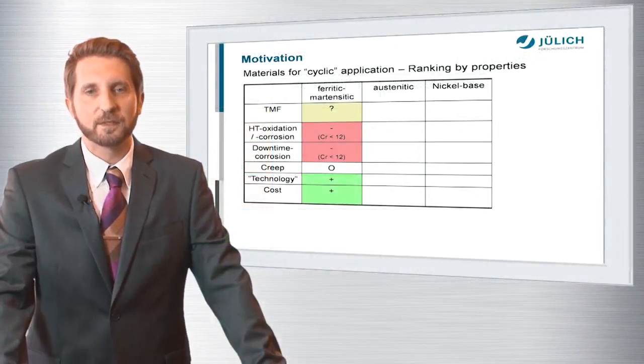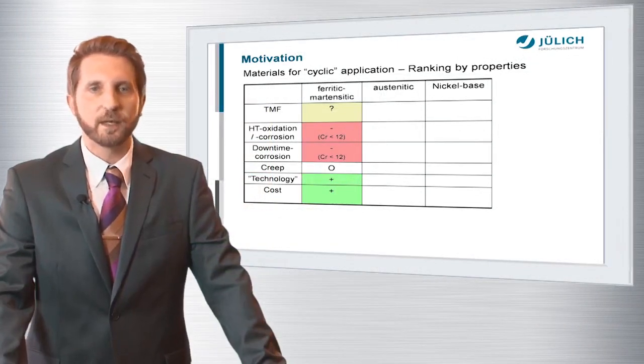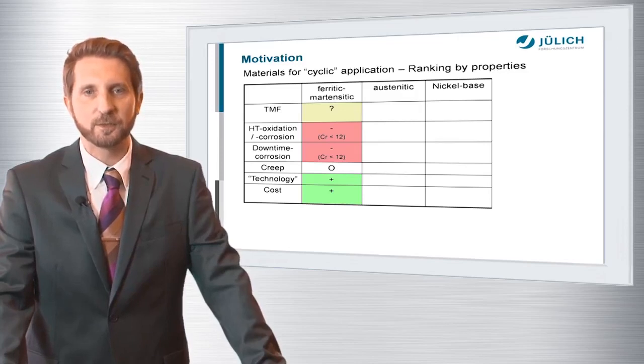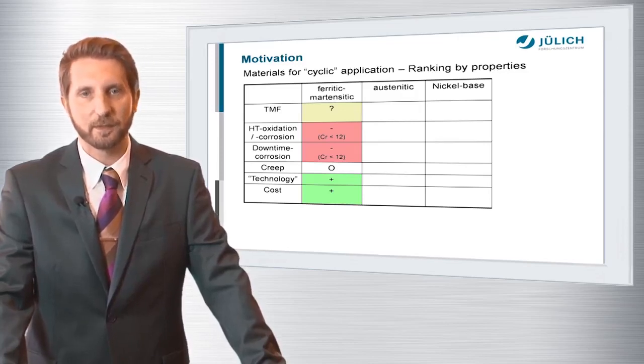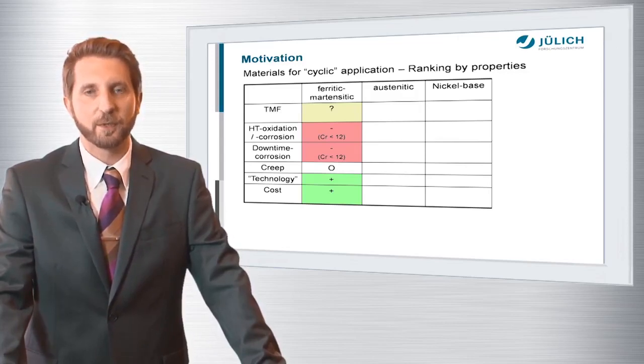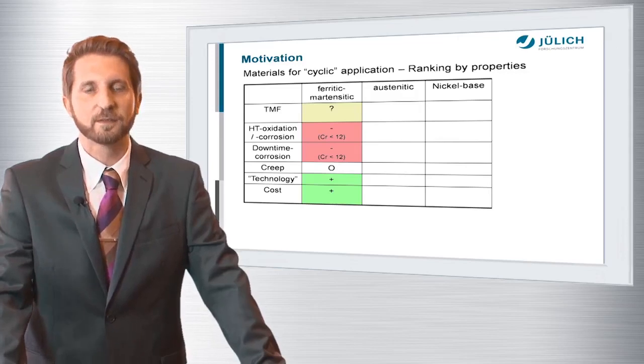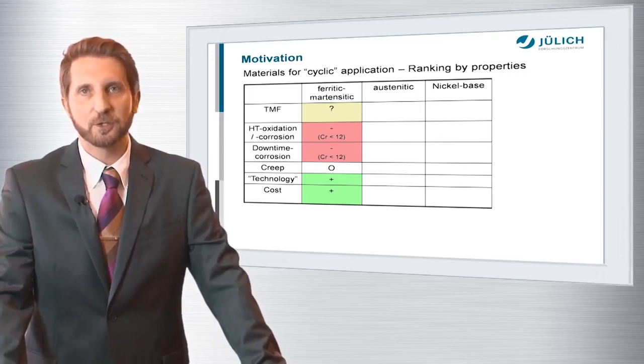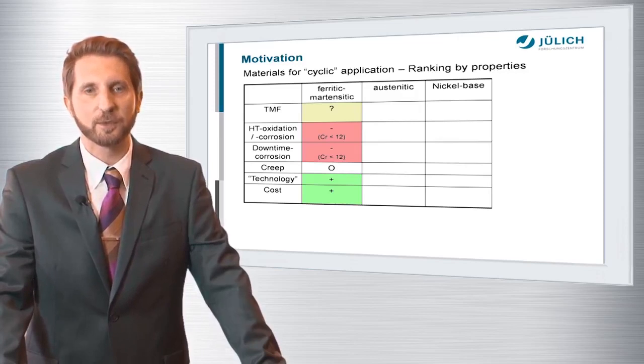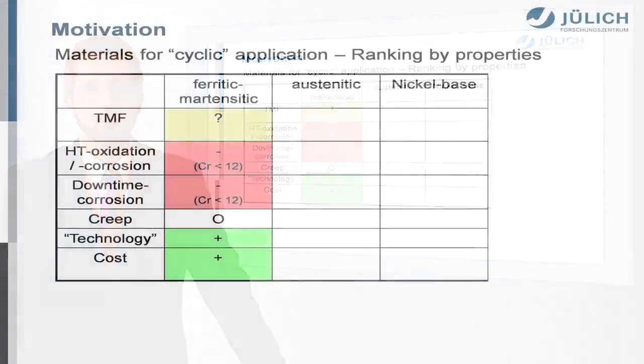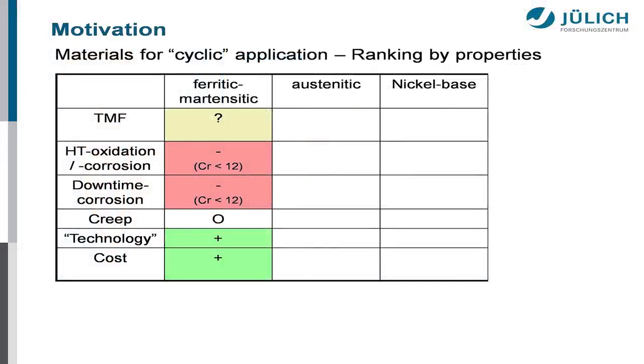All the ferritic martensitic materials are right now clearly limited by their high temperature oxidation and corrosion issues because of the relatively low chromium contents of about 12%. Creep is a property which is okay because they have been designed for that. Technology means all the issues which are touched by production of semi-finished products, of components, and the construction and erection of whole power plants. This is not a problem because the materials are state-of-the-art, and cost is not a real issue because these are the benchmarking materials.